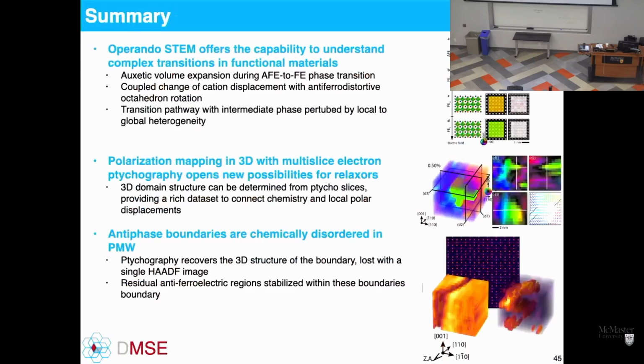Okay, so to very quickly summarize, we can do operando STEM, applying an electric field in the microscope, which allows us to really study the structural responses, the phases present, and ultimately, at the atomic scale, what gives rise to property changes. With multislice electron ptychography, we can reconstruct the functional properties of materials that have really been out of reach previously. These very complex materials with a lot of chemistry and polar changes, and phase changes through the depth of the sample can now be extracted. And as well, we can even look at chemical disorder locally, in this case at an antiphase boundary, to understand its influence on local structural distortions that can, again, modify the properties.